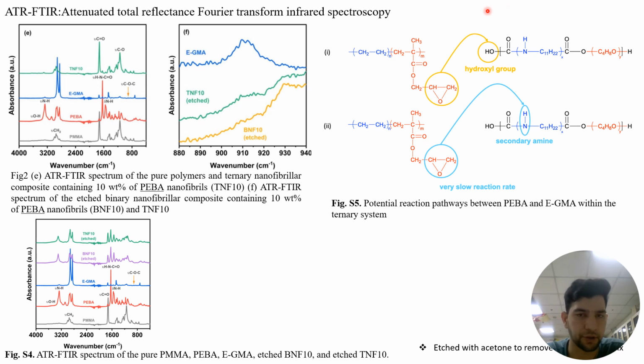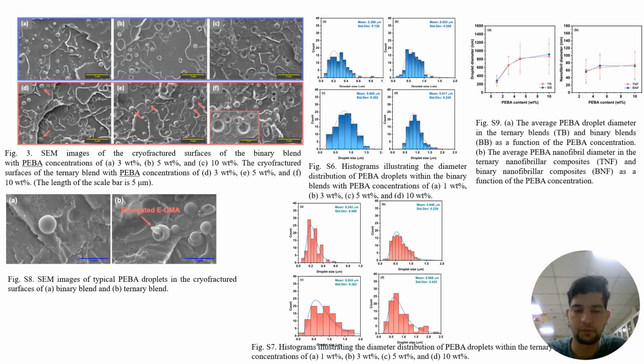So it is a possibility that during the compounding process these reactions happen, so that's why the peak of the epoxide disappears. And also here we see they make another bond, a hydrogen bond was also observed. So this is the interesting point, that the peak disappeared. So they are involved in a certain reaction.